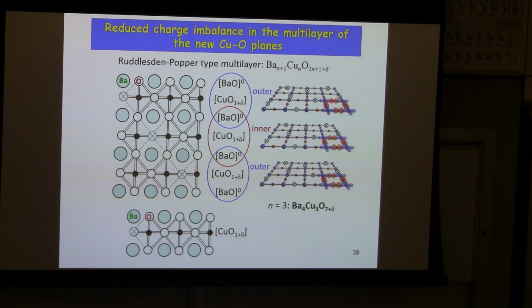If you look at the environment surrounding the oxygen plane, you can see that this Ba-O layer is basically electroneutral. Again, electroneutral Ba-O layer, these are sequences. You can see that there is basically no difference between the outer layer and the inner layer for the electrostatic environment of the oxygen plane. So there is no possibility to stop TC rise or reduce TC for the multilayers as we have encountered for the conventional cuprate. So this is my own proposed compound, which we expect to have higher TC, higher than 135 K, realized for three-layer mercury-based cuprate compound.